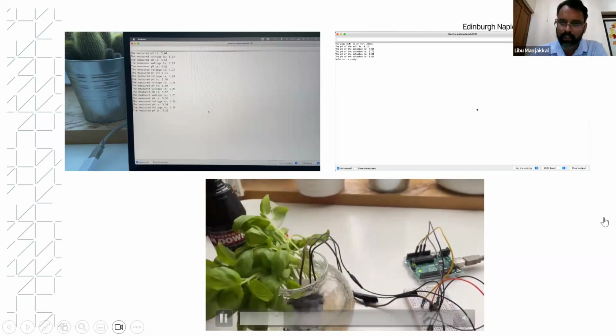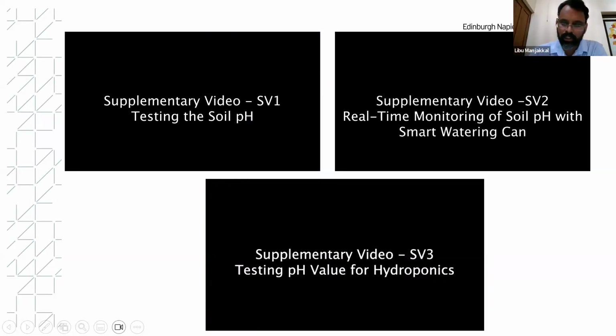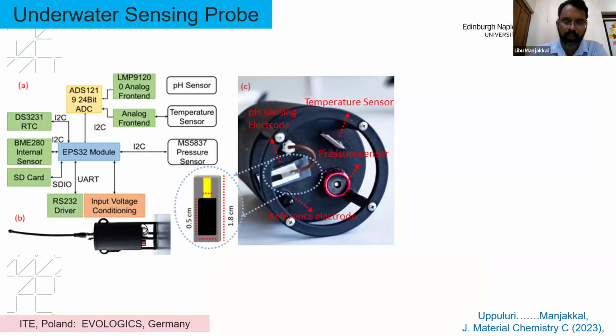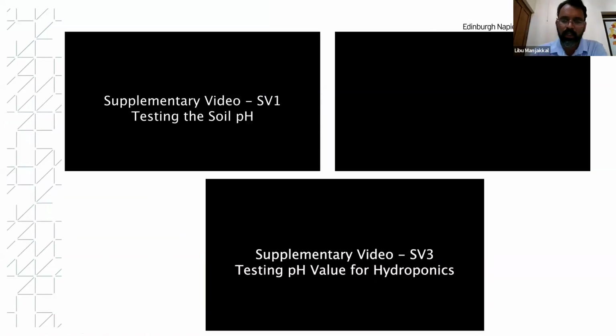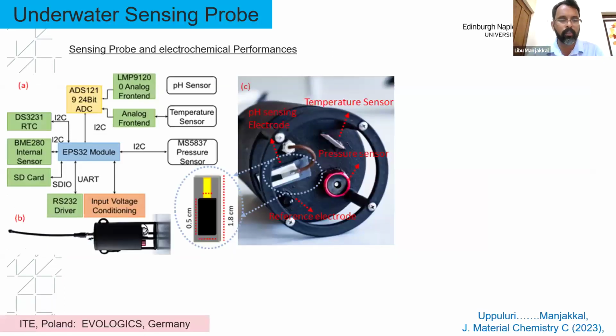So I found that the sensors we fabricated using printed electrodes, those screen printed electrodes, have a very good application for soil monitoring, especially if you need a rigid substrate like an alumina substrate, because glass based sensors have an issue when you put them in the soil, since they may break or lose their coating. So in this case, the screen printed thick film based sensors have a very good application for such an implementation.